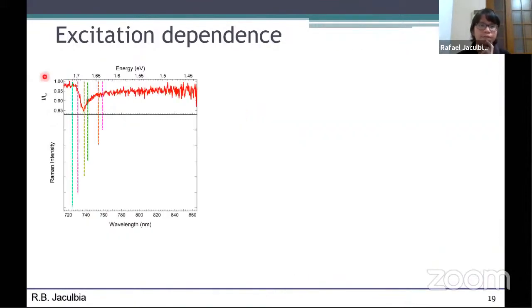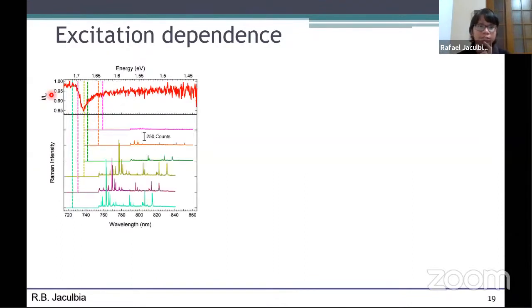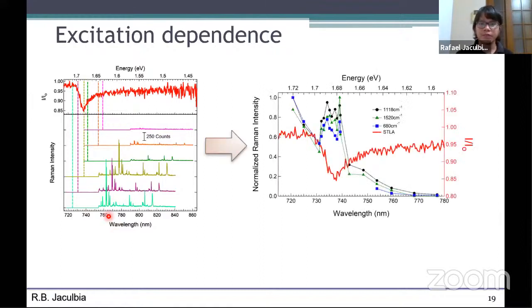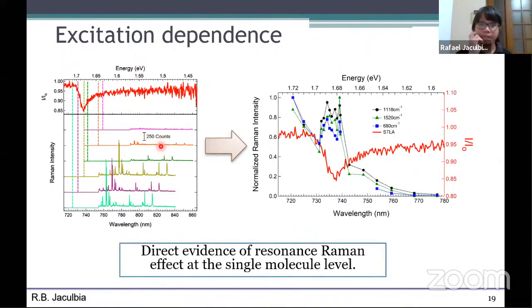So what I did is I varied the excitation laser wavelength around the absorption of the molecule. As I showed before, the Raman signal is very sensitive to the incident light energy. I found that the Raman signal changes a lot, and when the energy is lower than the absorption of the molecule, there is almost no signal. When we plot some peaks here, we can observe that the intensity varies exactly as the absorption of the molecule. This simply means that when the molecule is excited at its absorption, it shows a very strong Raman signal, as is expected for resonance Raman spectroscopy. So this is direct evidence of the resonance Raman effect at a single molecule, because in this experiment, we can only see one molecule.